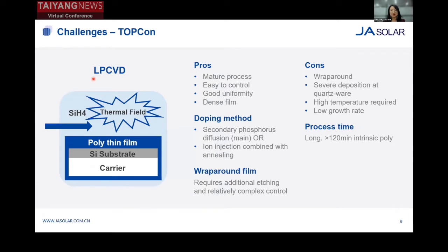LPCVD is the first and widely used deposition method for TOPCon solar cell processing. Although in situ doping can be realized by LPCVD, due to poor uniformity, most manufacturers instead prefer the approach of intrinsic poly followed by phosphorus diffusion. One of the challenges is the wraparound film, as can be seen from this picture. The poly thin film is not only deposited on the front surface of the substrate, but also at the side and back side of the substrate and on the boat.